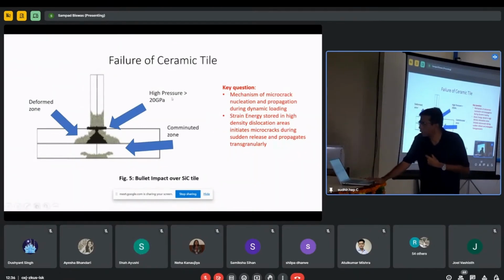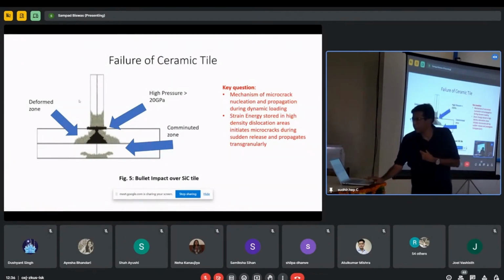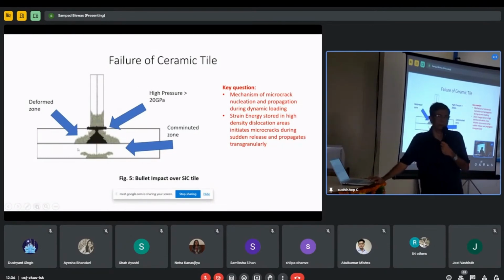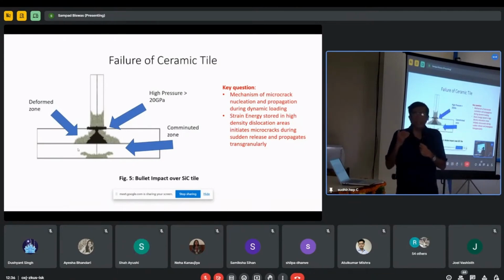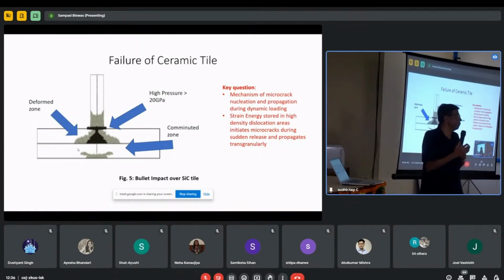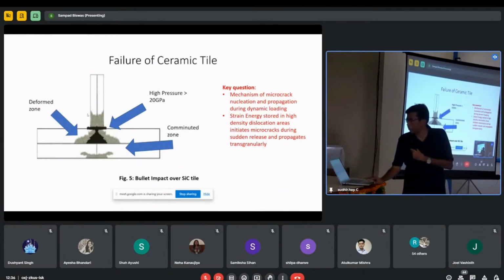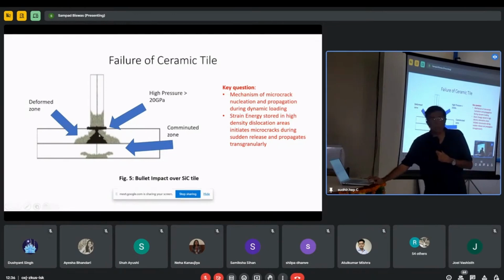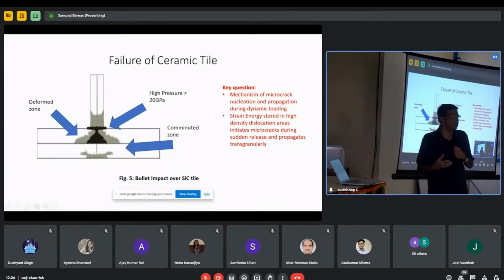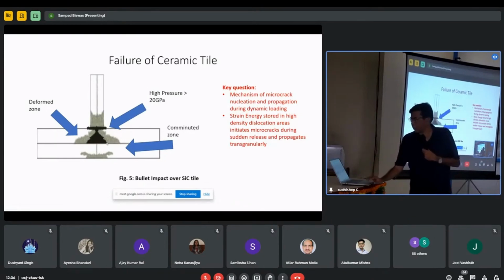which helps us to understand the mechanism of failure. If you look at the diagram, this is the projectile. When it hits the ceramic at a very high velocity, that means it has a very high kinetic energy, the tip of the projectile deforms and the ceramic also breaks. If you can delay this breaking of the ceramic, you can restrict the failure. The tip of the projectile, when it hits the ceramic, creates a conical crack. These conical cracks are quite common in anything under impact load and shock wave conditions.